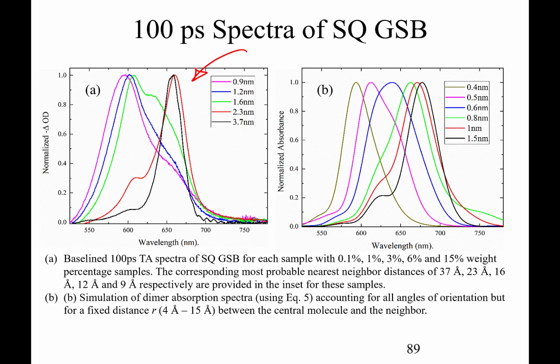So this is a dimer absorbance spectra, and we've actually changed the separation distance from 1.5 nanometers, that's 15 angstroms, to 0.4 nanometers, and what we see is this sort of blue shift that makes sense, that actually looks somewhat similar to the blue shift that's seen in the experimental data.